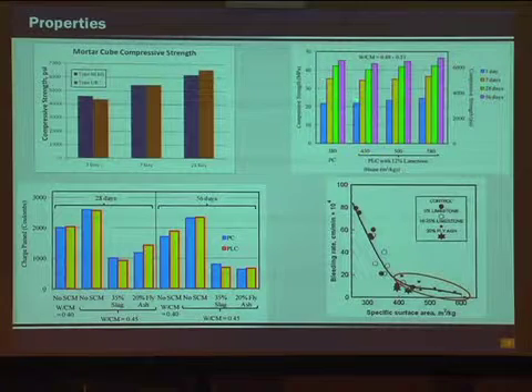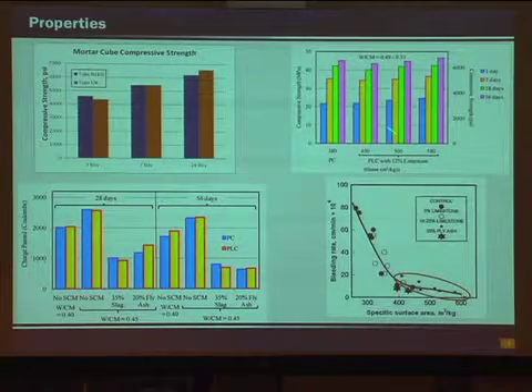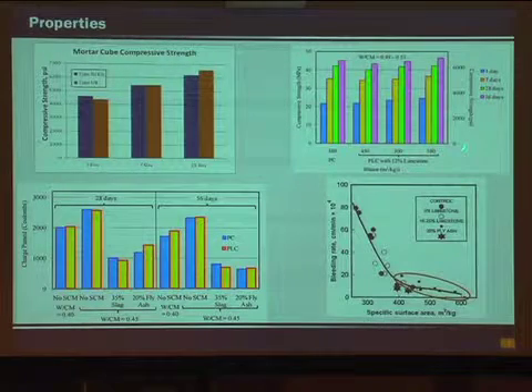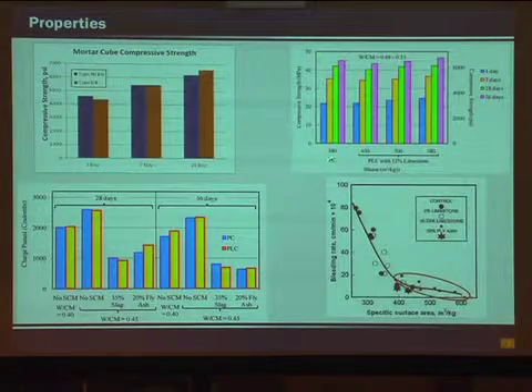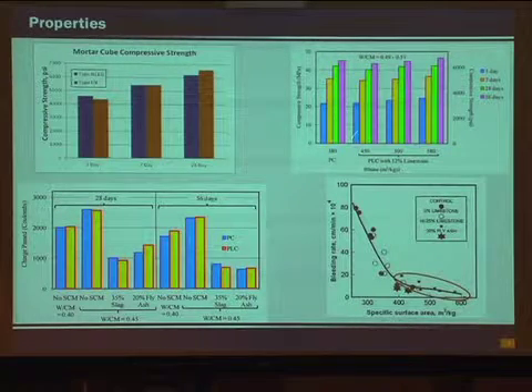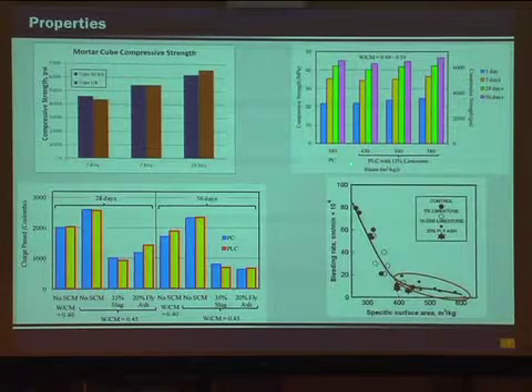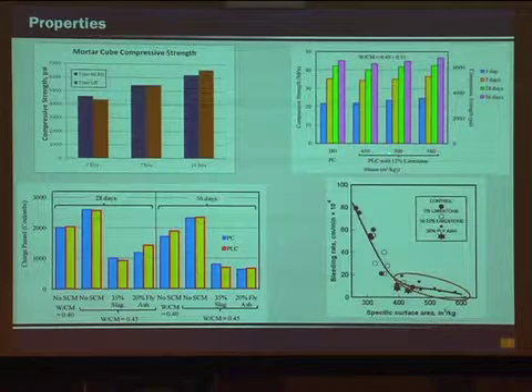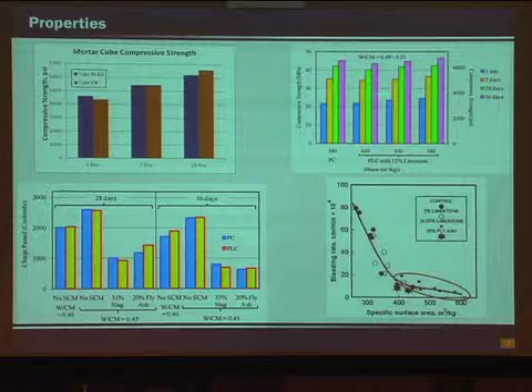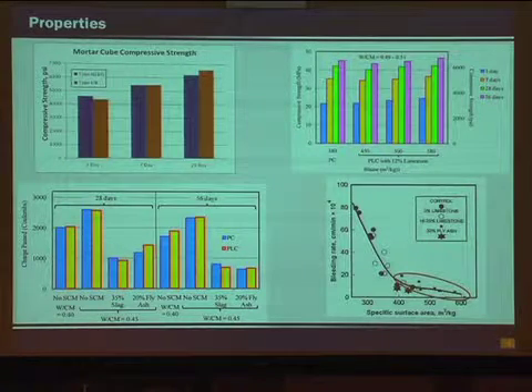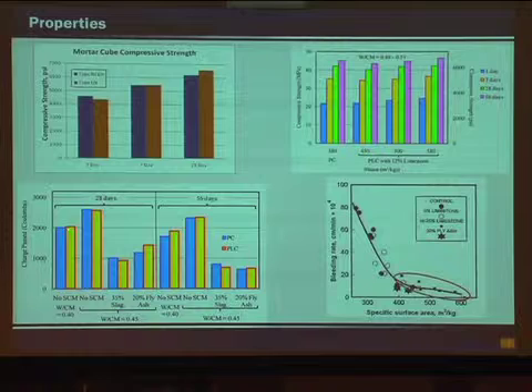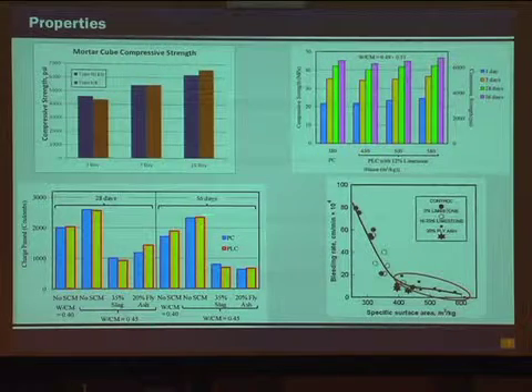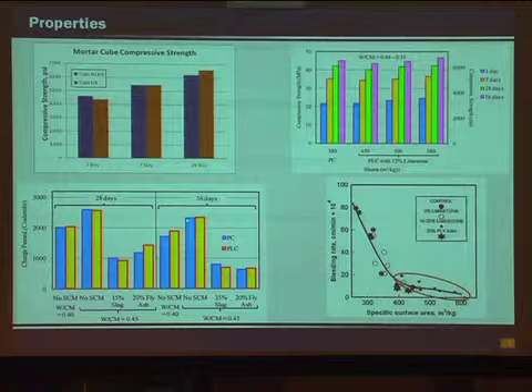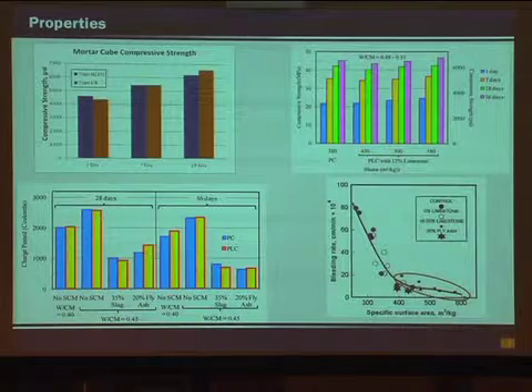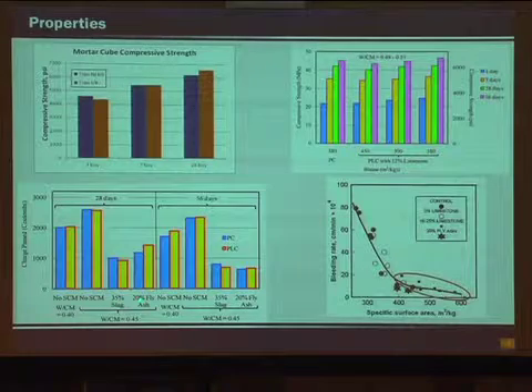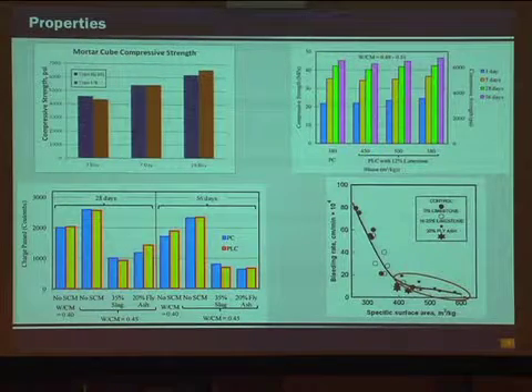cement. Here's some more data showing compressive strength of different limestone cements. And down here is that fineness I was talking about. You have your typical Portland cement with a Blaine value, which is an indication of fineness, at about 380. And then with the 1L cements, you get a little finer to achieve that same compressive strength. Some permeability data, again, no major differences between the two cements, the blue being the standard cement and the yellow being the PLC. And that's with slag or fly ash additions, so no major differences.